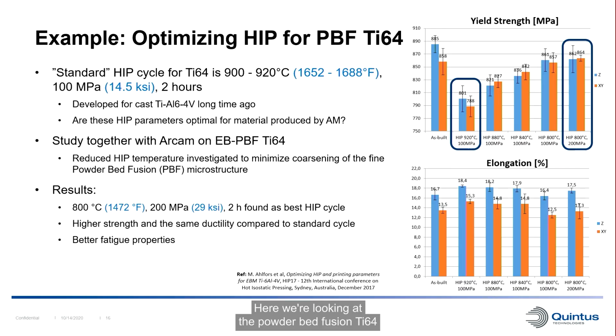Here we're looking at powder bed fusion Ti-6-4. And the standard cycle for this material that's typically used in the industry today is 900 to 920 degrees Celsius, 100 megapascal, for 2 hours. And this cycle was developed for cast Ti-6-4 a long time ago. So one question is, are these parameters really optimal for additive manufactured material, since the starting microstructure is often quite different?